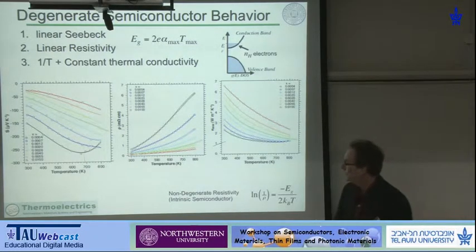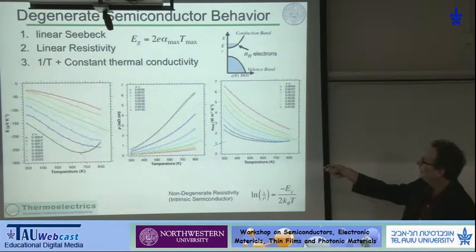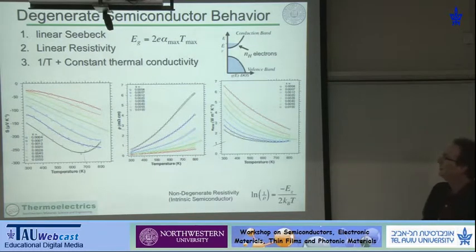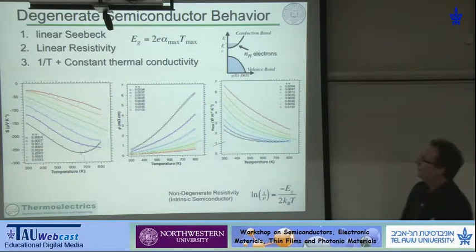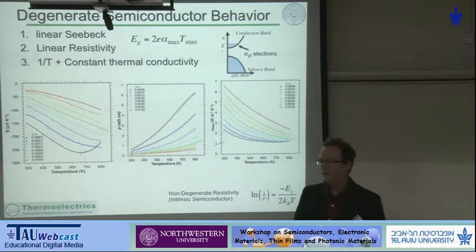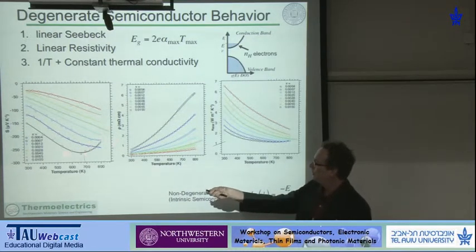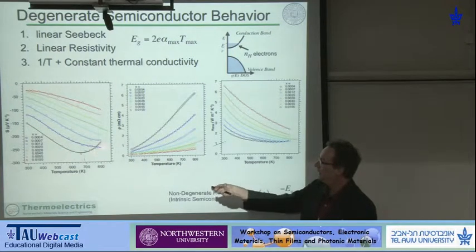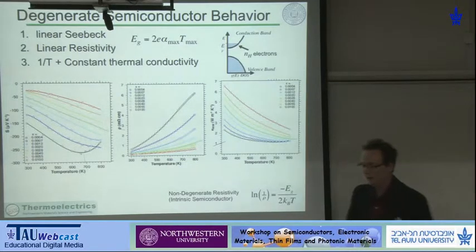For the thermoelectric properties, we also need to understand the thermal conductivity, and the thermal conductivity of a semiconductor includes the electronic contribution, so we need to take care of that, and there's also some bipolar thermal conductivity that will come in as well. One of the things we like to do is since we use these at high temperature, we need a high temperature band gap. The Seebeck coefficient is a very nice way of measuring the band gap. When we see the Seebeck coefficient roll over, we can correlate that with the electronic band gap.